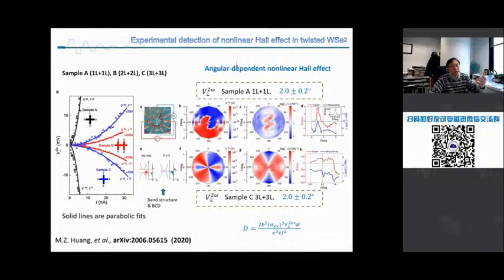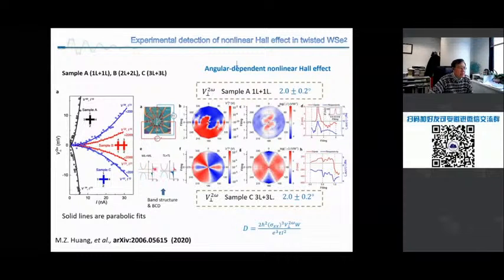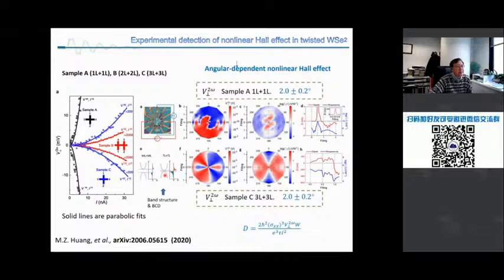All right. So this is the band structure. The Berry curvature dipole happens here. Conductivity and the band. Monolayer, trilayer. All right. So we can make a circular device to detect the Hall voltage in all directions. And surprisingly, we detect signals in all directions. That is different from the previous ones. Previously, they had mirror symmetries, and perpendicular to the mirror directions, you would see 0. But this is not. This is not.